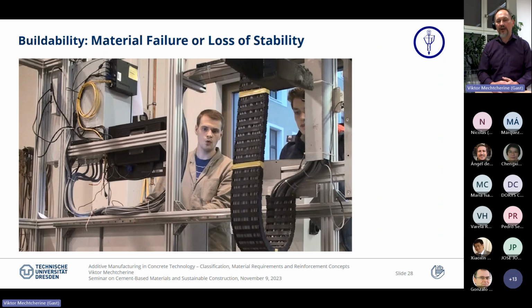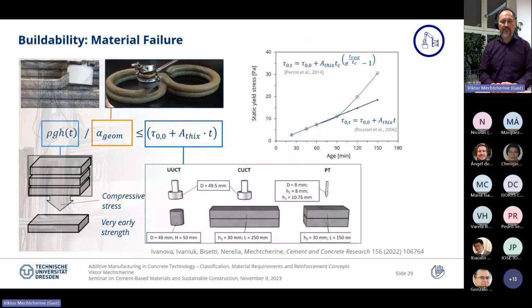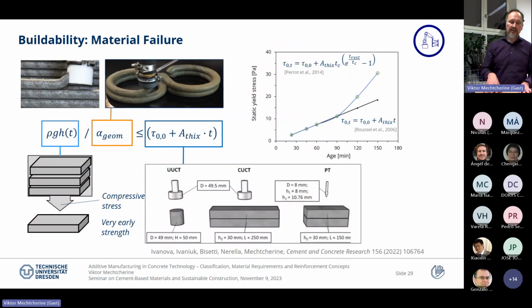So in this case, material failure, due to flow of the material, of the first one or two layers of the material. Another scenario is the loss of stability, where you have, due to elastic deformation of the wall, which becomes higher and higher and higher, some stability issues. And I'm really talking about elasticity, even if the material is not really hardened, but it has some elastic properties and it's decisive here. And of course, it can be also a mixture of some plastic deformation plus then loss of stability in addition. So it means that here again we need to describe the material resistance.